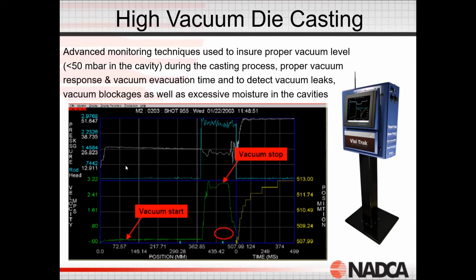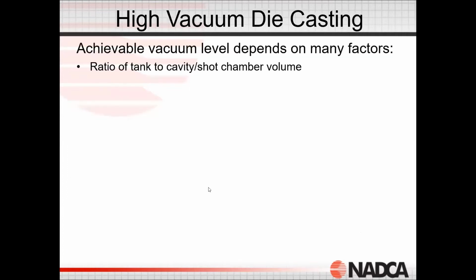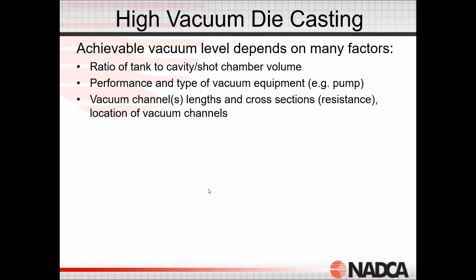So we look at these shot profiles and we can tell whether we're getting a good casting. And then within those profiles, we can not only measure the vacuum levels and the shot, but we can also measure the humidity levels. So we can actually determine if we have excess humidity creating porosity in the die casting.